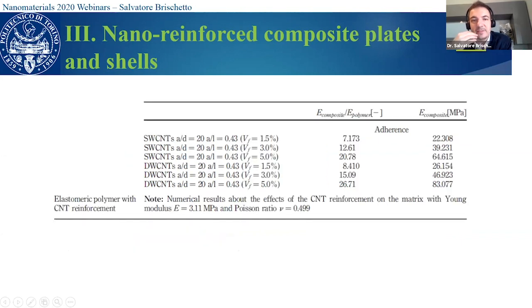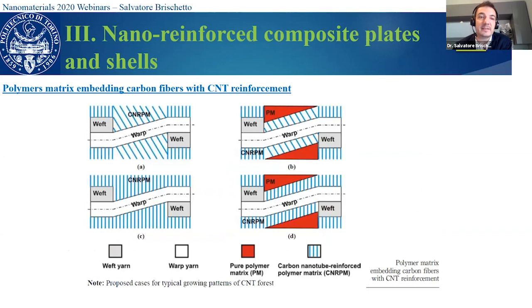These are other similar results in this sense. So we have a comparison between single-walled carbon nanotubes reinforcement and double-walled carbon nanotube reinforcement with the adherence and with different volume fractions. Another possibility is we have a matrix and we have the typical fiber, rectilinear fiber reinforcement. So we can add some carbon nanotubes on these fibers in order to improve the adherence between the matrix and the carbon fibers. Okay, and there are several possibilities to add these nanotubes as reinforcement.